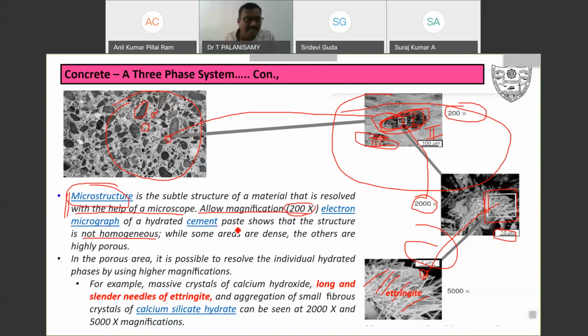Now, the structure is not homogeneous. Some areas are dense and others are highly porous. This area may be dense in nature, this area may be porous in nature. In the porous area, it is possible to resolve the individual hydrated phases by using higher magnifications. For example, massive crystals of calcium hydroxide, CH, and long and slender needles of ettringite. I will tell you what ettringite is.